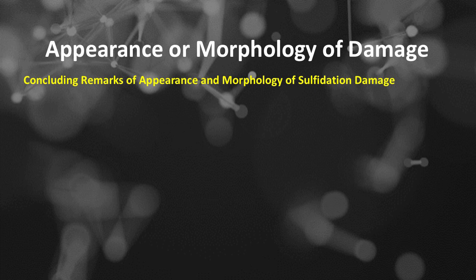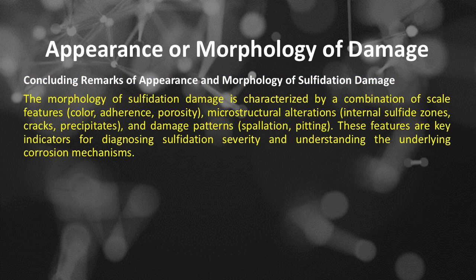Concluding remarks of appearance and morphology of sulfidation damage. The morphology of sulfidation damage is characterized by a combination of scale features, color, adherence, porosity, microstructural alterations, internal sulfide zones, cracks, precipitates, and damage patterns, spallation, pitting. These features are key indicators for diagnosing sulfidation severity and understanding the underlying corrosion mechanisms.